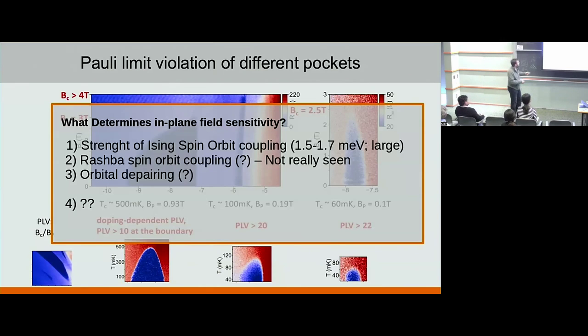Another thing that is considered seriously is this orbital depairing. With orbital depairing, you just apply a magnetic field in plane, and because these wave functions live on both top and bottom layers, you could think that there is some depairing happening because there's a flux penetrating through this delocalized wave function. But these displacement fields are large, so the question is how much you can explain away with the orbital depairing, okay? And is there any other mechanism that could play a role? That's something to keep in mind.